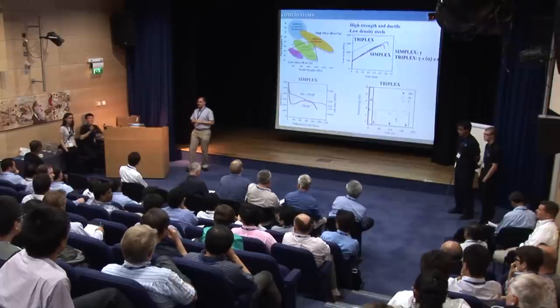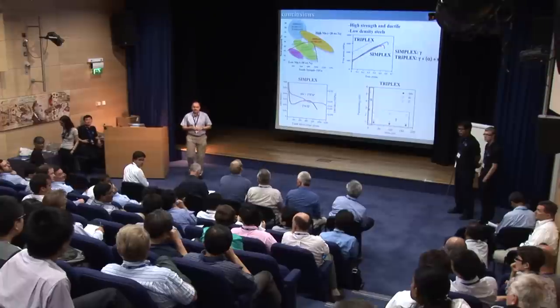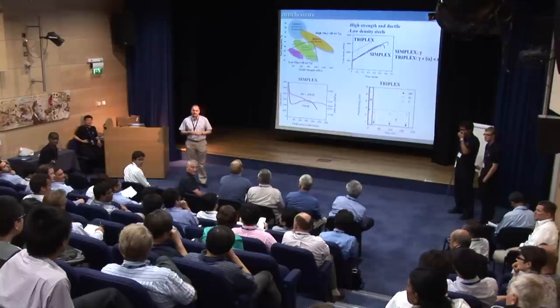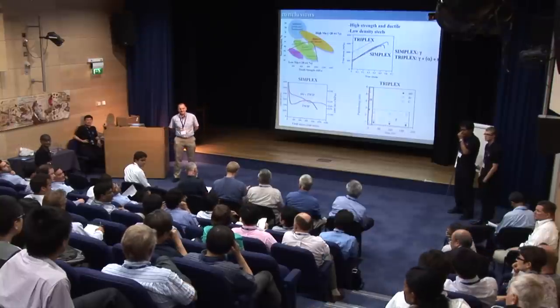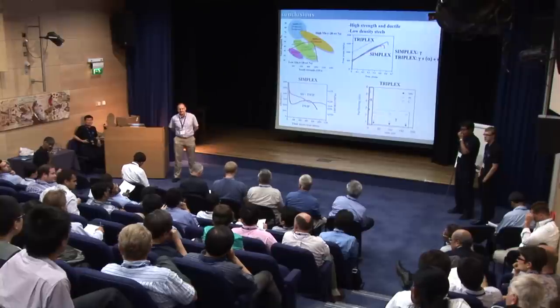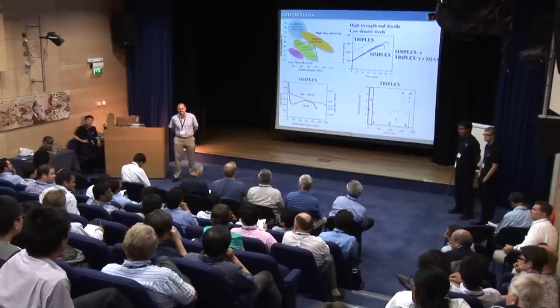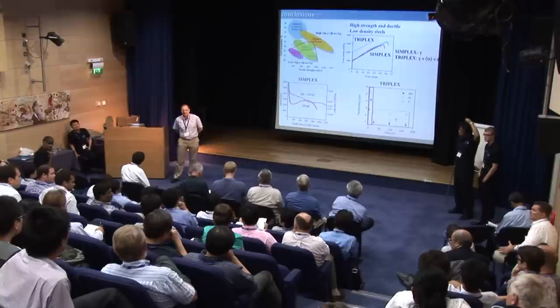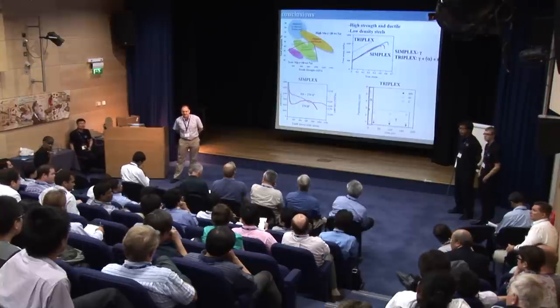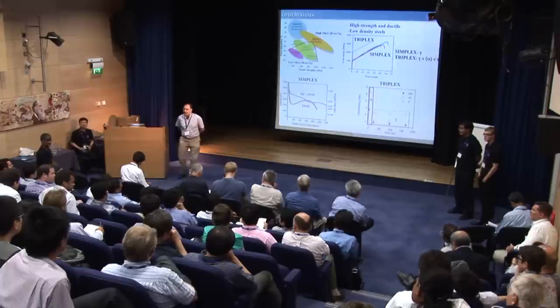My question is not really a scientific one. Each time I see this low density, I have a little problem with that. I know that when people develop high manganese steels, or medium, or in your case even low manganese steels, you put in a little bit of aluminum and some silicon, and probably up to 1% or more carbon. But that doesn't really reduce the density much, does it? Yes, that's the point. It's just a comment. You are completely right. So where is the attraction? It's the aluminum. But in triplex we only add, let's say, 10%, 12%. The question is, can you call these low density steels?